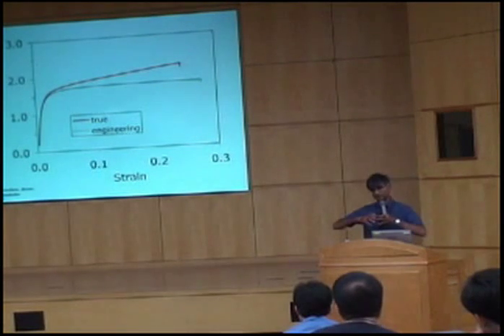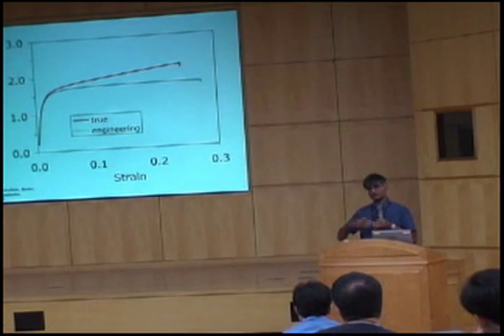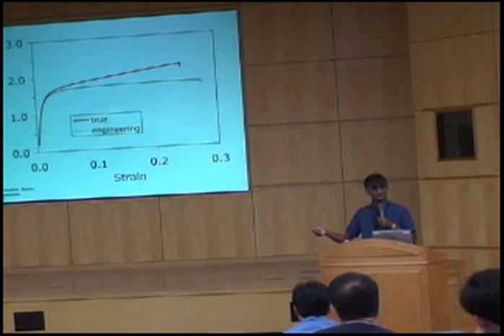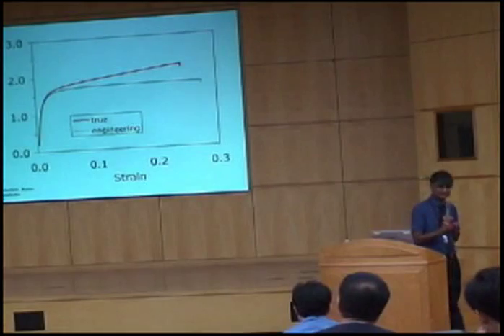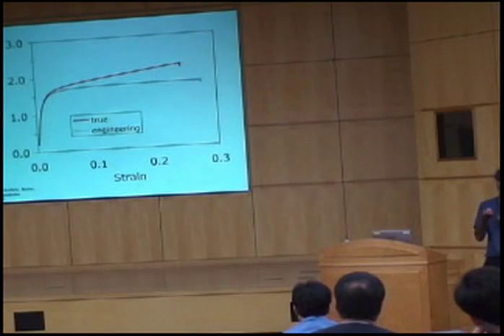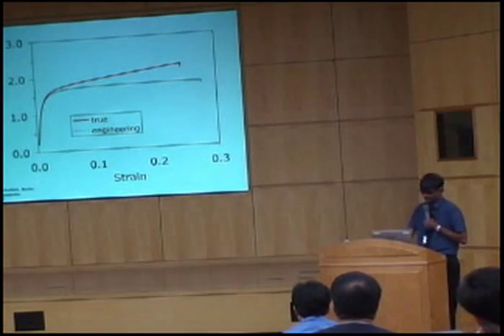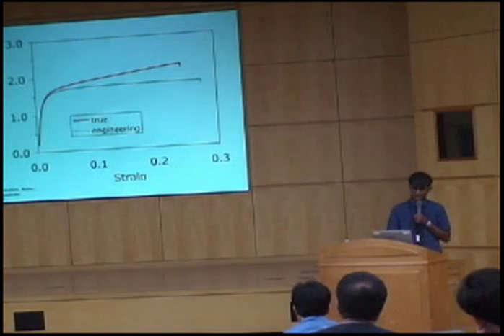Well, of course, when we pull these steels, the austenite is undergoing phase transformation, stress and strain-induced transformation to martensite. And that's the reason why these steels are good. The TRIP effect gives you a higher toughness. It cancels out stress concentrations.